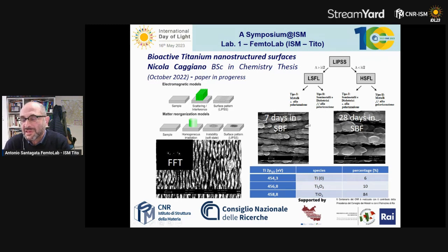The LIPSS can be split into different regimes. Low spatial frequency LIPSS, when the spatial period of our nanostructure is roughly comparable to the wavelength of our laser, or high spatial frequency LIPSS, when the spatial period of our ripples is much less than half of the wavelength of the laser. In terms of application, we have seen that these nanostructures, these ripples, can be very useful for increasing the absorbance of some materials like diamonds, as we saw in the previous movie.